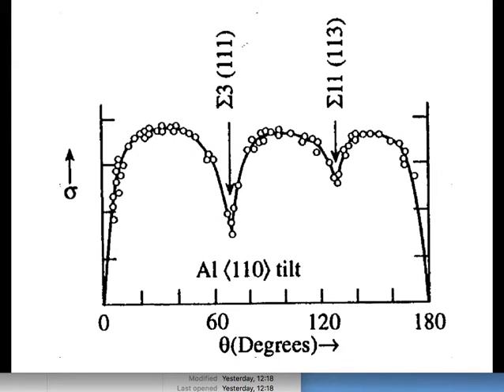Okay. And this is just to show you how experimental measurements of the interfacial energy per unit area, for in this case a 110 tilt boundary, that means you're taking the two crystals and tilting them about the 110 axis, and you see these very sharp cusps in interfacial energy. I'll explain the terminology sigma 3. Sigma 3 means that one third of the lattice points are in coincidence.